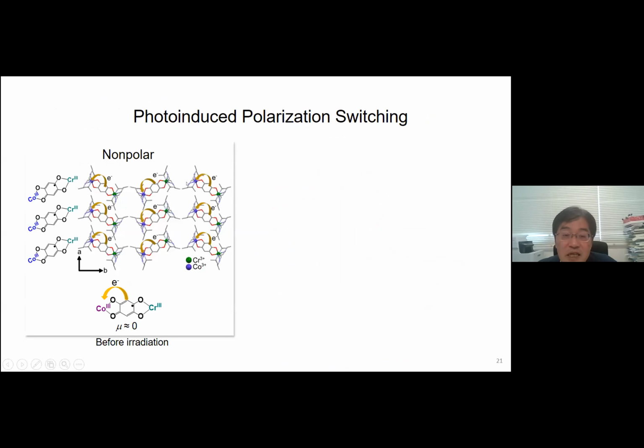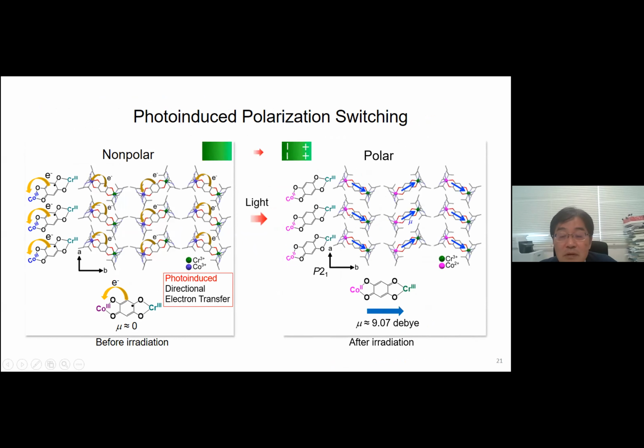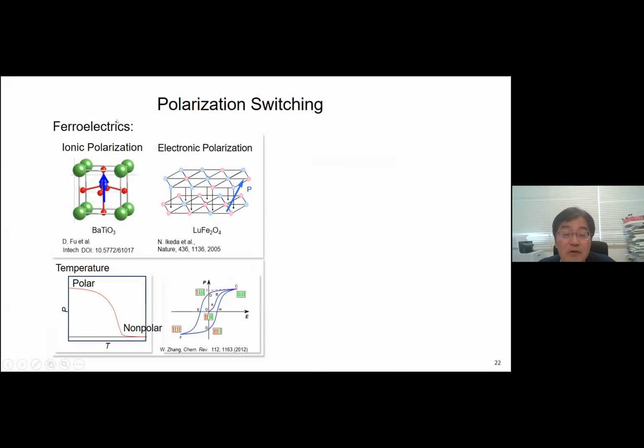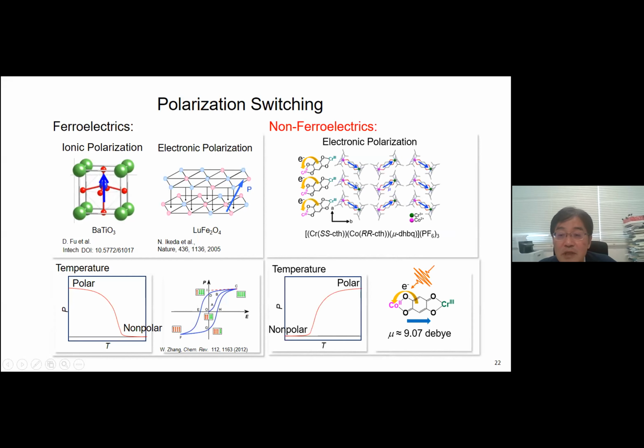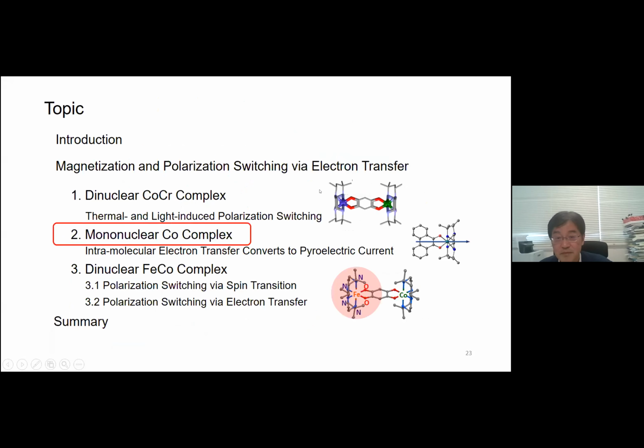So this molecule is irradiated, then photo-induced directional electron transfer is induced from here to the cobalt-3 site, forming a polar state. And the time scale is 280 femtoseconds. So ultra-fast photo-induced polarization switching is induced in this cobalt chromium single crystal. And as I mentioned, in ferroelectric compounds polarization switching is observed, but now we realized polarization switching using electron transfer, using directional electron transfer, and furthermore, polarization switching is induced by photoirradiation. Okay, this is the first topic.